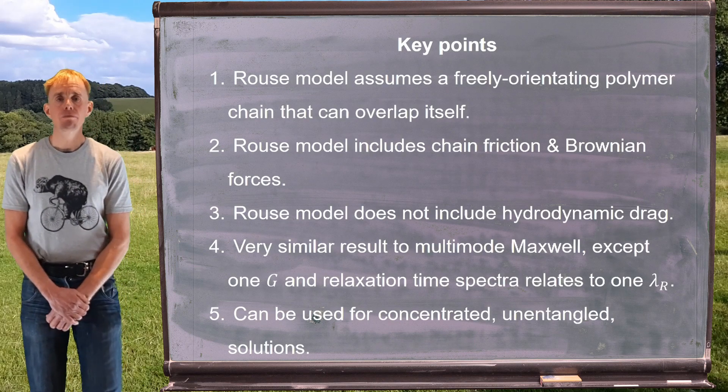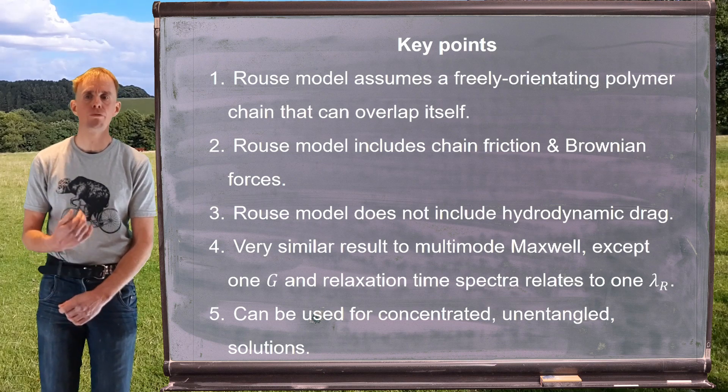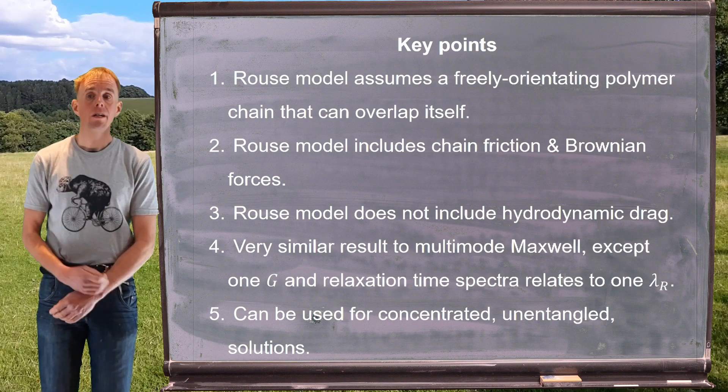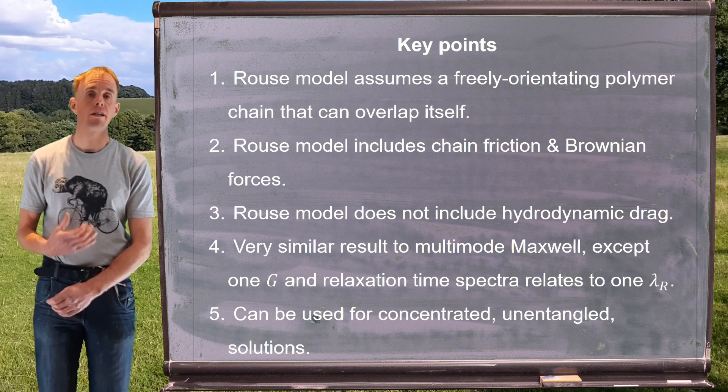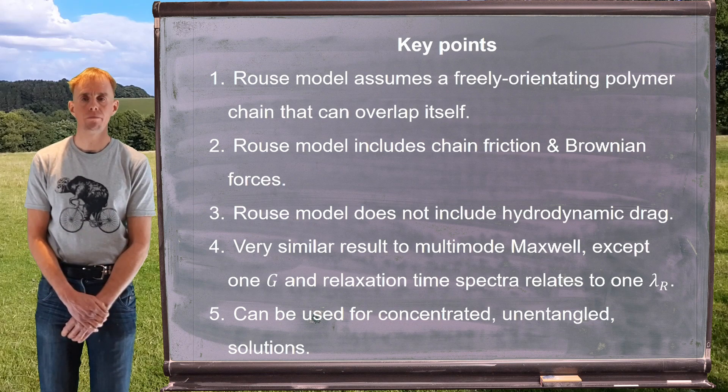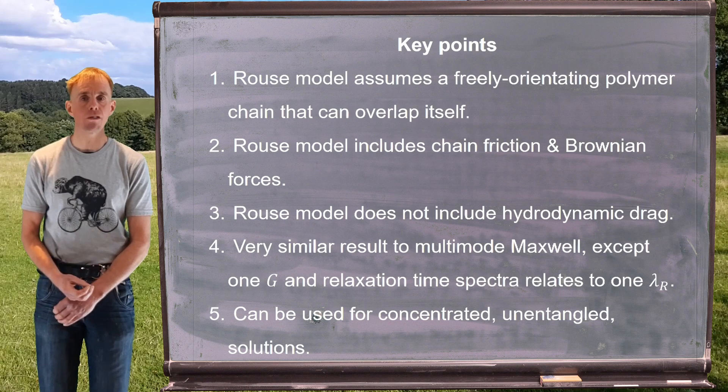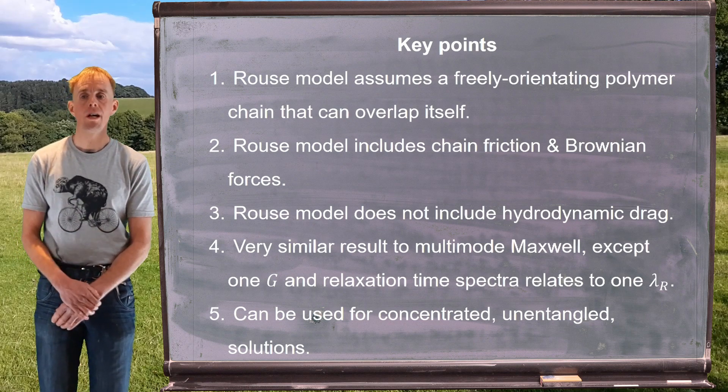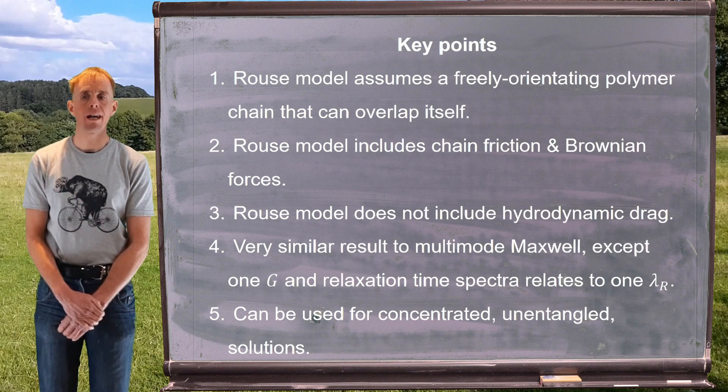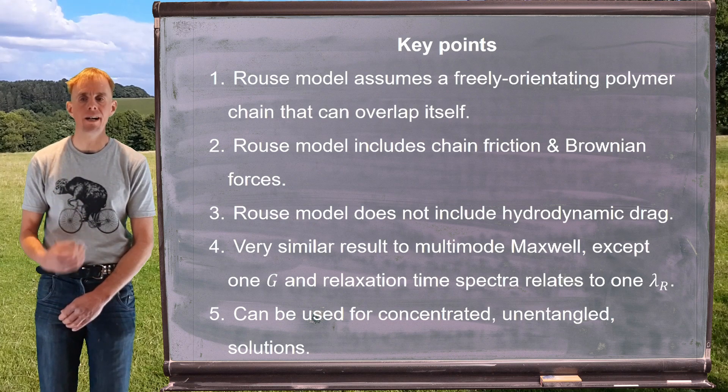Let's recap a few key points. We've looked at the Rouse model and the Rouse model assumes a freely orienting polymer chain that can overlap on itself, a Gaussian chain. The Rouse model includes chain friction and Brownian forces, but it does not include notions of hydrodynamic drag. When the derivation is complete, we get a very similar result to multimode Maxwell, except that we only have one modulus, G₀, and the spectra of relaxation times can be related to one relaxation time, λ_R. The applicability of the Rouse model is for concentrated and unentangled solutions.